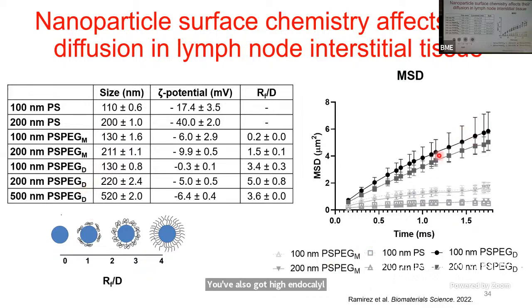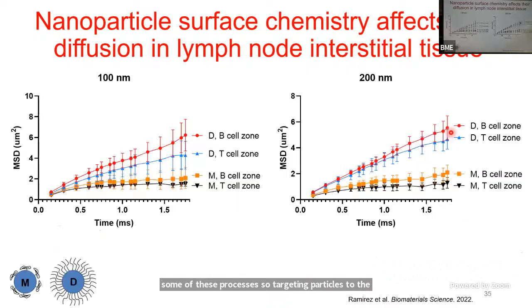And we found that when we have the dense PEG coating, we get pretty good diffusion of those particles within, of course, you know, ECM and cells and so on. So it's a little bit stunted compared to if you were doing this just in water. And we found that this holds true no matter what region you're in. So in the B cell and T cell zones, you get better diffusion of the particles when they're densely pegylated compared to just having a little bit of PEG on them.